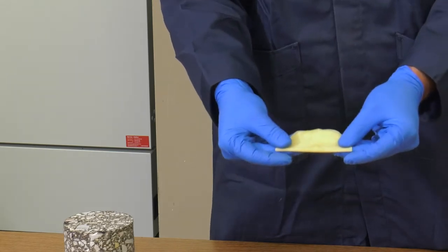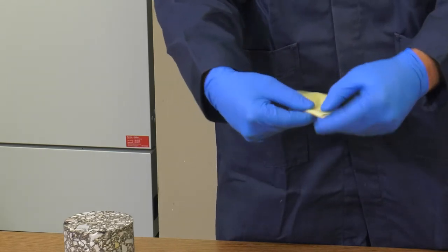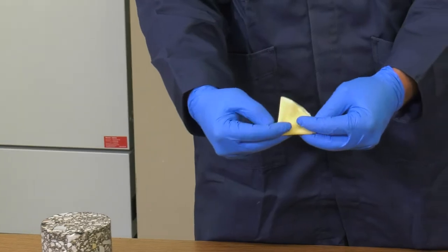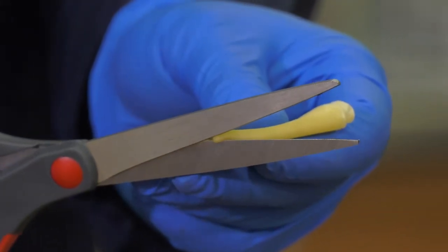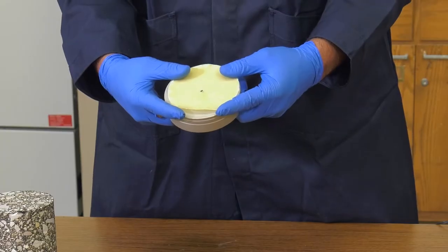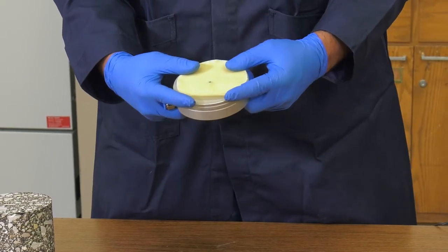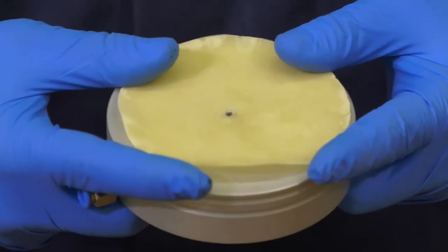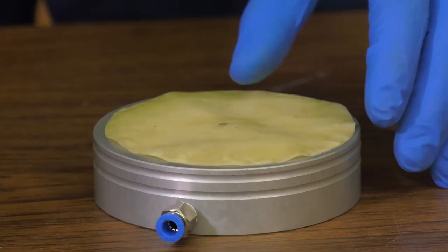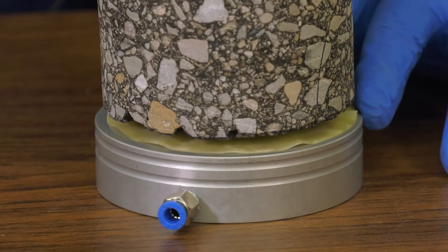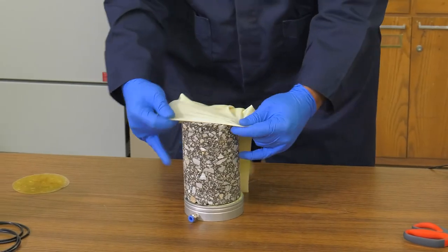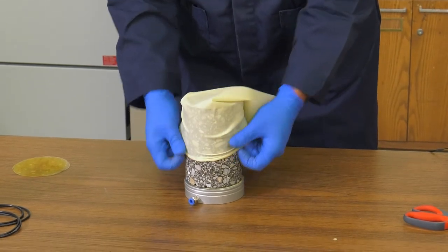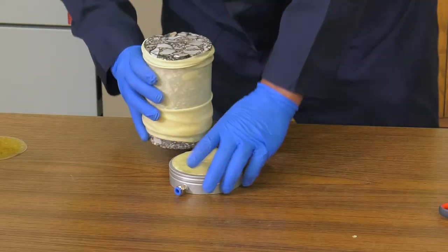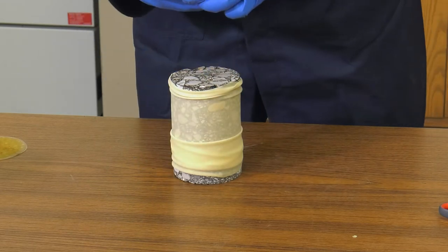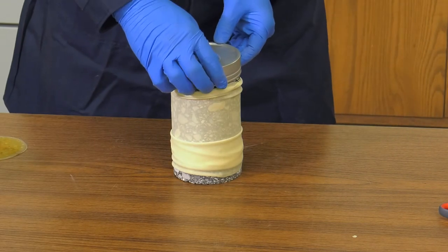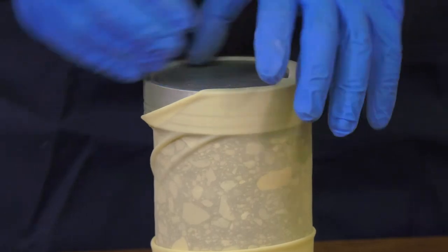Repeat the steps to create a double-layered membrane. When assembled, fold it into quarters and then cut off the point of the fold to make a hole or punch a hole in the membrane. Unfold and align the hole on the membrane with the vent on the lower platen. Place the specimen on the lower platen and cover with the membrane. Stretch the membrane around the base.